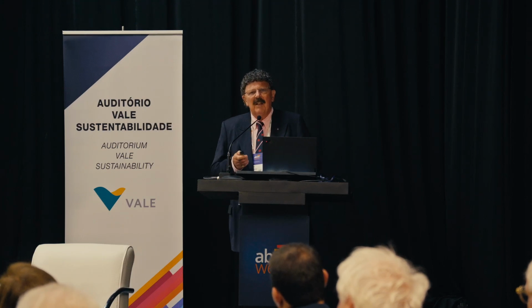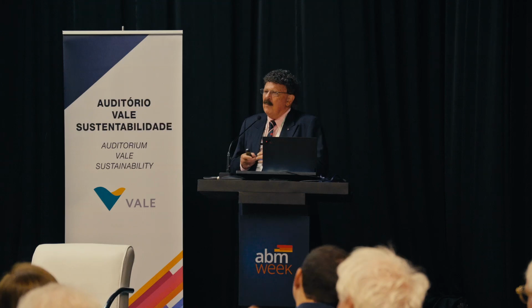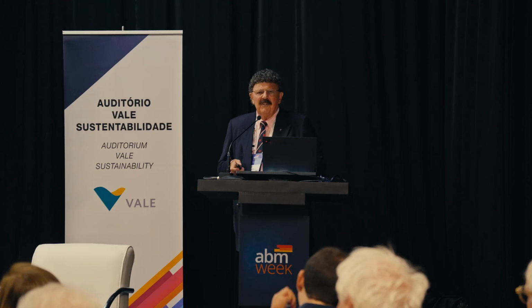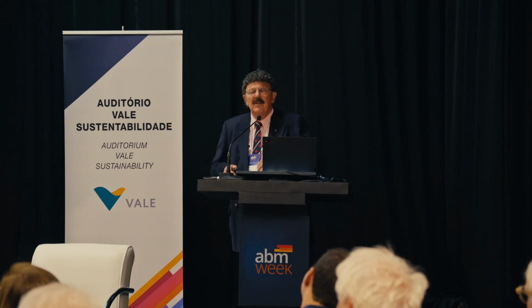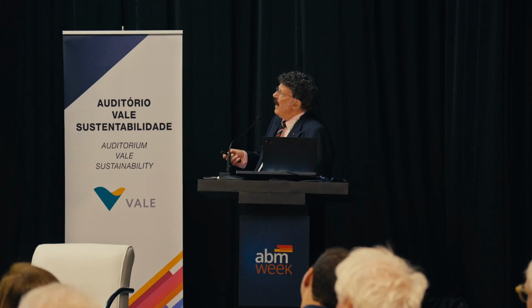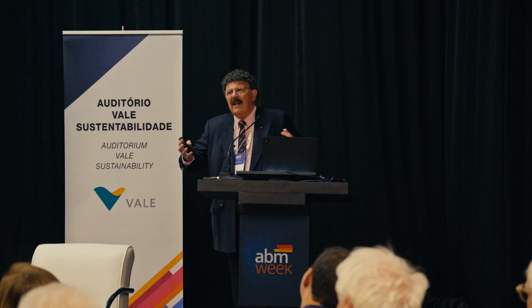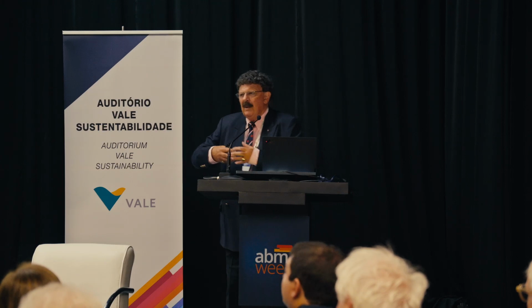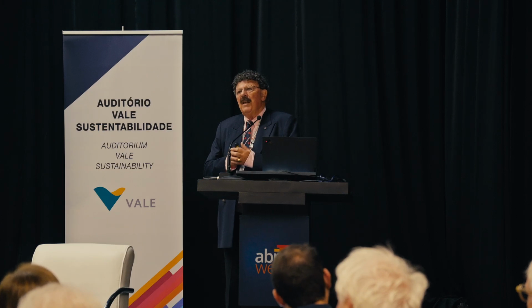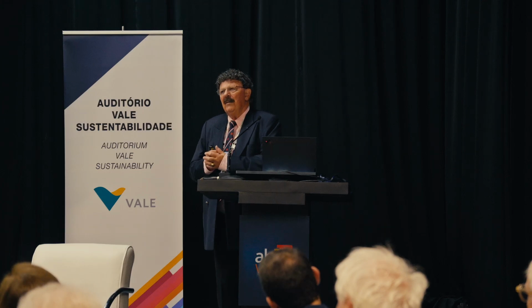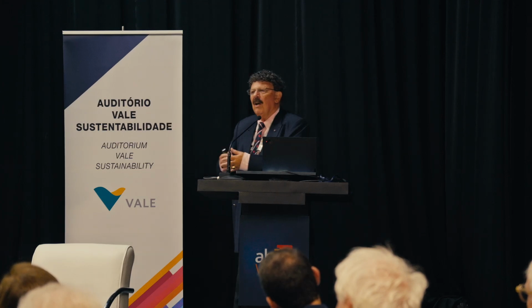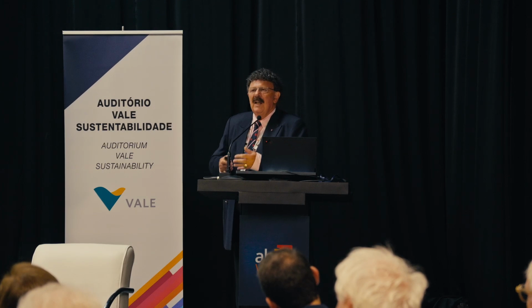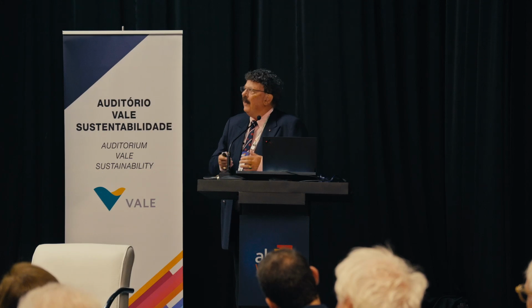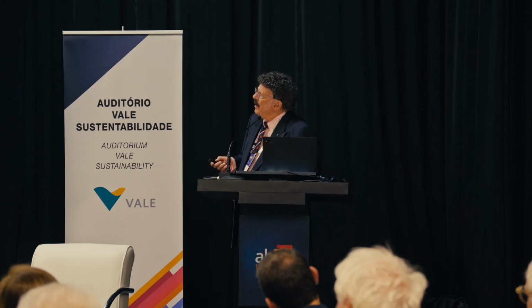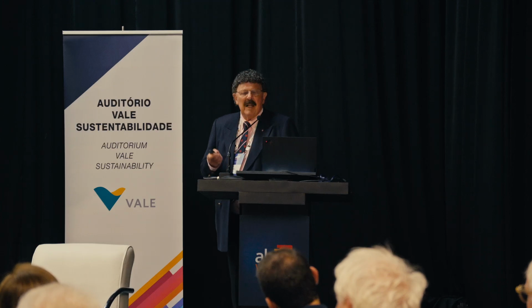So what is the ductility of these materials? Well, that's a key, of course. They all have strength with these multiple principal elements, but the ductility is what gives them the toughness combined with the strength. In the FCC, I've explained it's a sequence of mechanisms: deformation, slip, stacking faults, twinning, and then the formation of a phase transformation gives you prolonged strain hardening, and that gives you high toughness. And we think these alloys are probably the toughest ever formed.